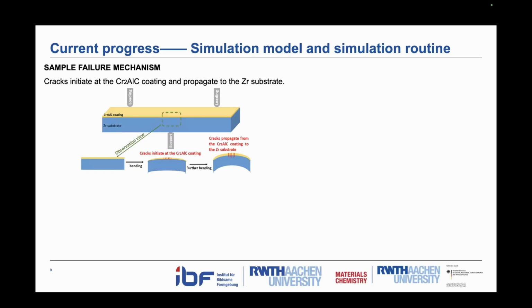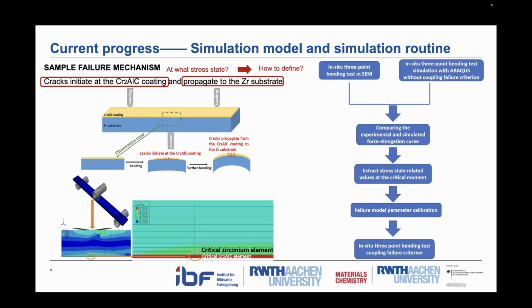Then comes the next question: at what stress states do these two critical moments happen, and how can we define these two critical moments? Due to the difficulty of recording those stress states in the SEM, we have used an alternative method, which is numerical simulation. What we did follows the routine on the right side. We carry out in situ 3-point bending tests and also simulations, without coupling any failure criterion yet, simultaneously. And we compare the experimental curve and the simulated curve, the force-displacement curve.